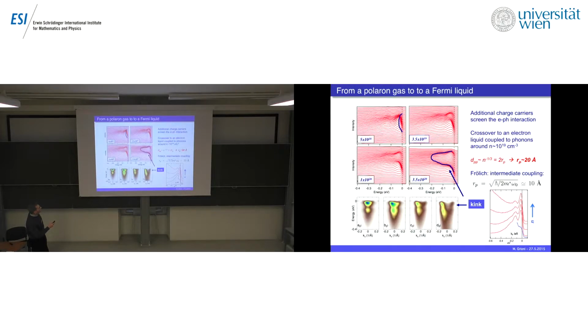Let me skip this. Now, the interesting thing here is that one can change the density of carriers, and the spectrum changes in a very interesting way. Not only does the band drop down from the Fermi level, because one is putting in more and more electrons, but also the shape is changing. Maybe it's clearer here. These are cuts at the Fermi wave vector. At low carrier density, this is the spectrum, as we saw before, and at high carrier density, well, there is a much stronger quasi-particle peak, and the satellites are weaker. And also, at large carrier density, the band is this parabolic thing, and there is a kink.